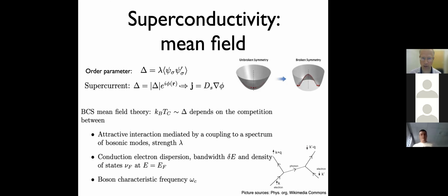Now, my approach to this is to ask how to relate the size of delta to the band structure, and I use the BCS mean field theory to get there. Here delta generally depends on the competition between an attractive interaction, which is usually mediated by a coupling to some spectrum of bosonic modes, usually phonons in conventional superconductors. This attractive interaction has a strength lambda. And then we have the electronic dispersion. Electrons generally have some bandwidth and density of states at the Fermi energy. And then there is some characteristic frequency of the bosons which mediate this attractive interaction.